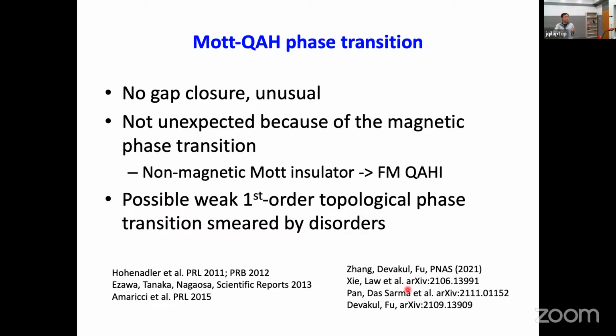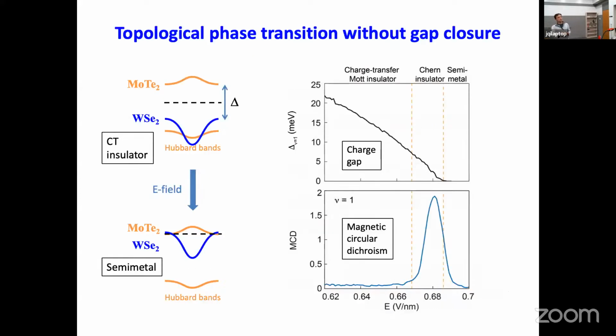But in the literature, there are actually different theoretical papers talking about the possibility of a topological phase transition without gap closure. It typically involves a change in the symmetry of the system, which I don't totally understand. But quite likely, what's happening here is a possible weak first order topological phase transition in the system. Then the jump in the charge gap at the topological phase transition, which in that scenario you would actually expect around this boundary here, is sort of smeared out by the disorder. But it's also somewhat surprising that you actually see the charge gap really evolves smoothly in this transition.